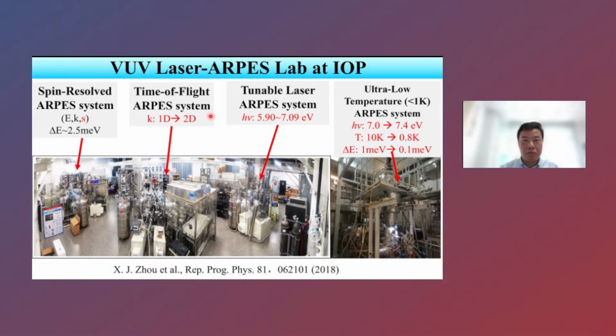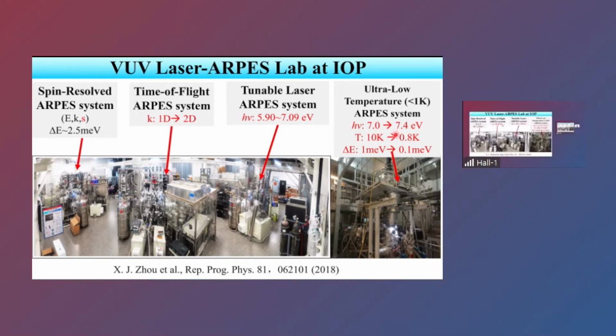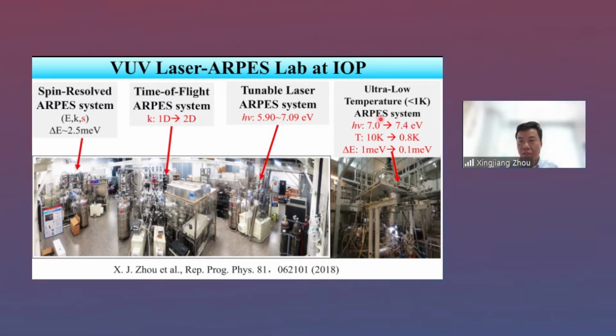Also, we have developed a system called the time-of-flight ARPES system. In this case, we can really measure 2-dimensional momentum at one time, so this is the measurement of momentum from 1D to 2D. And the fourth one is the one we just developed, the ultra-low temperature ARPES. In this system, we can cool down our sample to 0.8 Kelvin. I think so far this is the only ARPES system in the world which can cool down the sample temperature to lower than 1 Kelvin. Also, we further improved the energy resolution from 1 millielectronvolt to 0.1 millielectronvolt.